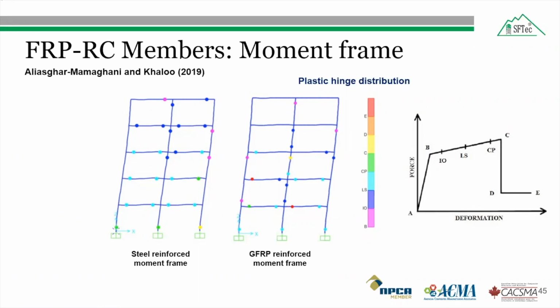So the top story beam of the GFRP reinforced moment frame doesn't provide ductile performance due to the linear behavior of the GFRP bars, which changes the failure of the frame from beam to column sideway mechanism, which is not desirable during an earthquake. Therefore, GFRP reinforced moment frames need attention to avoid such soft story phenomena, and this can be avoided by providing higher stiffness to the columns in GFRP reinforced moment frames.